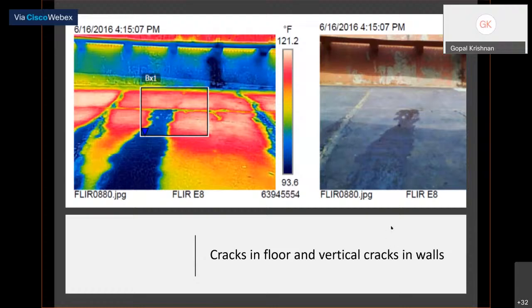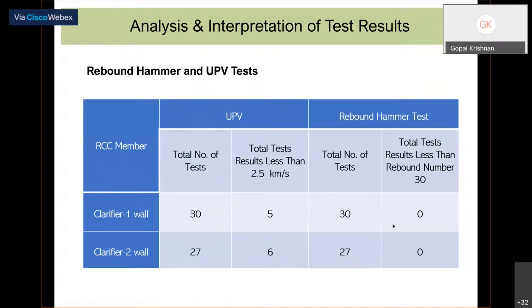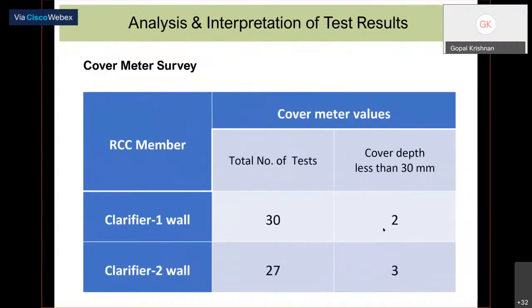Okay. And the results: we have used all the NDT. The UPV result was found somewhat satisfactory, only errors of 5% and 6% were below the satisfactory level. And rebound hammer gave a good result, about 30 rebound numbers. The strength is okay. But what are the other parameters? Even the cover is adequate, except 2 or 3 numbers that are not good. Otherwise, in the majority of cases the cover is 30 mm.